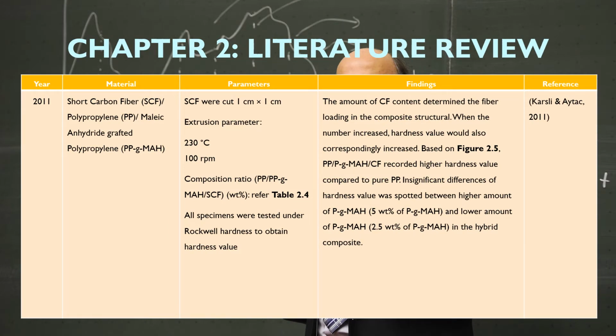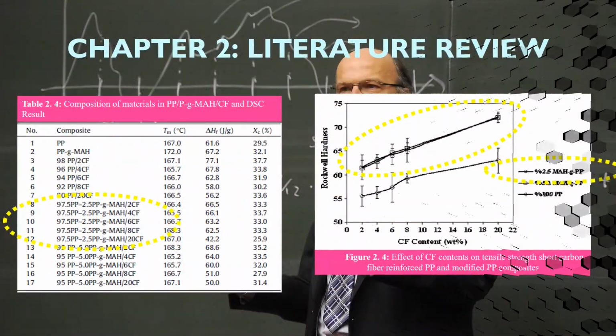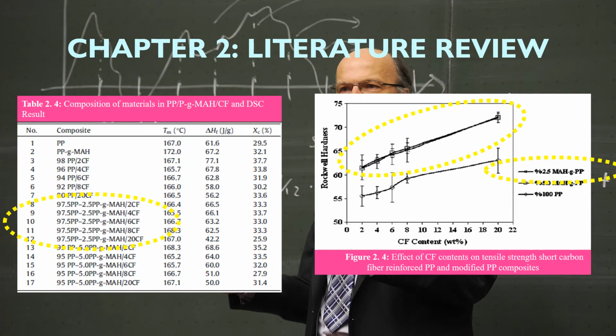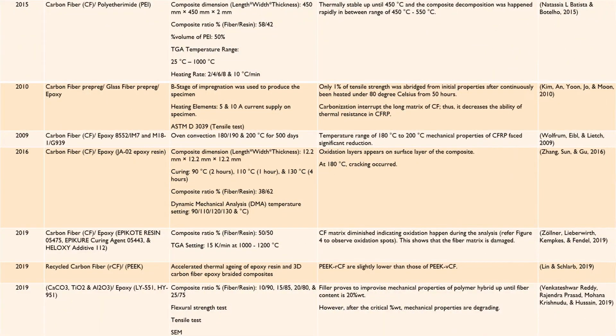Next, the finding on the hardness test based on Karsli and Aytac: carbon fiber content will be determined by the fiber loading. Thus, it affects the microstructure, which will influence the hybrid polymer composites. This suggests that adding carbon fiber will enhance the hardness properties. The result can be seen as shown in the slide. Besides, there are other studies on carbon fiber, and all findings show similar results for polypropylene matrix-based polymer composites.